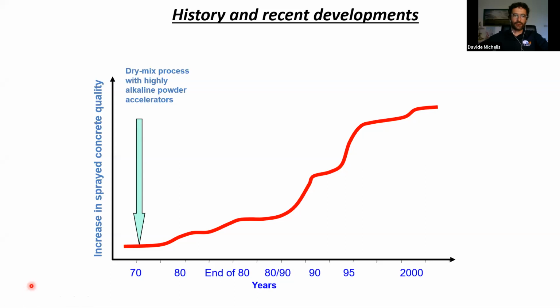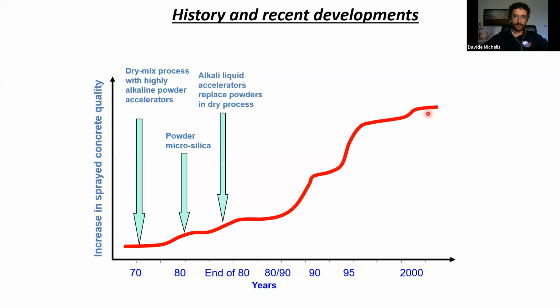So, starting from a bit of history about shotcrete, going back to the 70s, where the dry mix process was especially accelerated with alkaline powder accelerators. So we are really at the beginning of the technology employed inside a tunneling project. In the 80s, there is an introduction of powder microsilica in order to have a better mix design and extend the durability of the mix design.